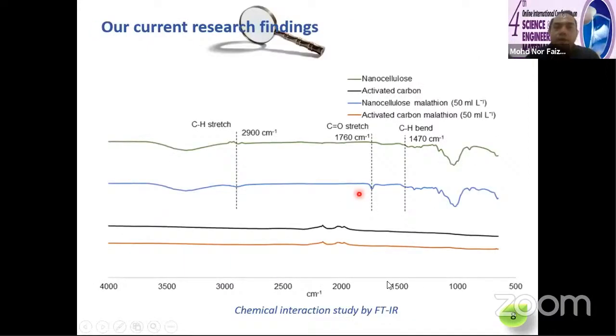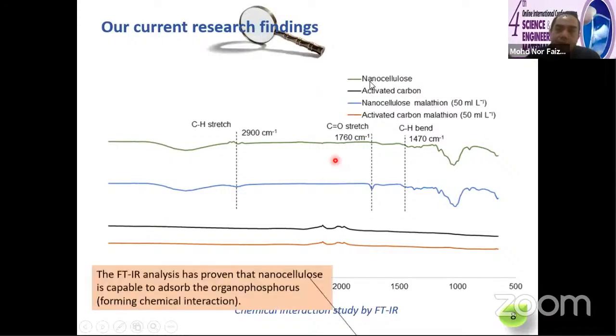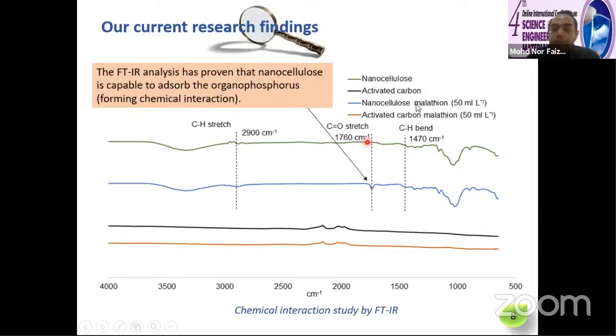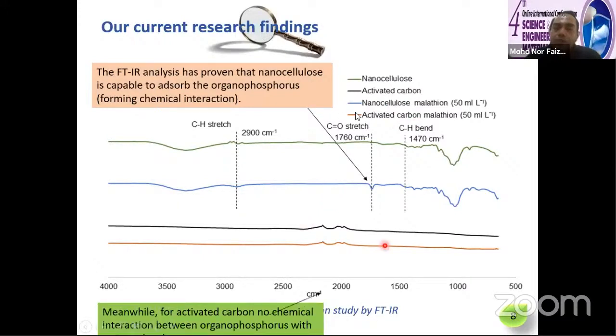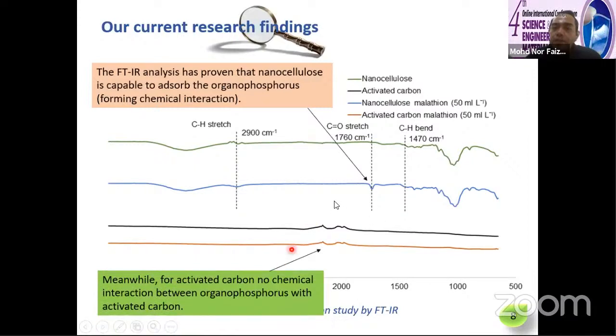So based on our current research findings, this is the chemical interaction study by FTIR. We can see that the nanocellulose, after being immersed with malathion, which is one type of organophosphorus that I use in my lab, shows the presence of a carbonyl stretch peak here, indicating successful interaction or binding of the organophosphorus to the nanocellulose, because only the organophosphorus has the carbonyl functional group, as I presented in the previous slide. However, for our activated carbon, no changes can be seen in the FTIR spectra, indicating that activated carbon cannot form a good chemical interaction with organophosphorus. It is just used to entrap the chemical compound.